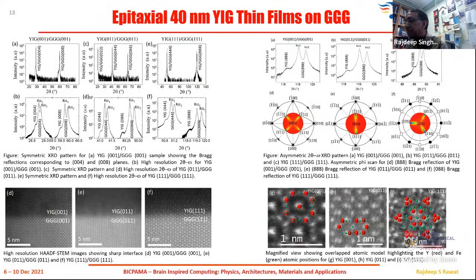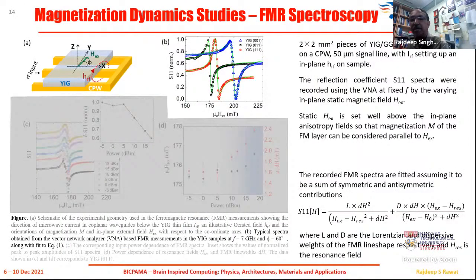Just a few words about the films that have been grown. They are 40 nanometer YIG thin films, deposited using magnetron sputtering. These results, the high-resolution XRD as well as the high-resolution TEM imaging, show that we have grown very good YIG thin films. The epitaxy is excellent. YIG films with different orientations, with different facets, have been deposited on different GGG substrates. There are three different films, with the three orientations 001, 011, and 111. We wanted to investigate how two-magnon scattering is affected by these facet dependencies.